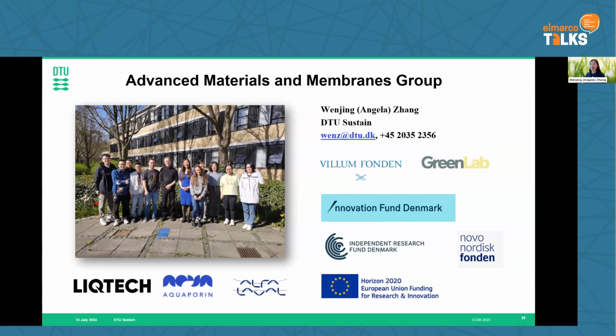Another from the audience. What do you think about core-shell nanofibers? Have you tried to use them in membrane technology, the core-shells? Yes, actually we did core-shell electrospinning, and then we did the carbonization to make a binary catalyst for zinc-air batteries. We have the paper published in Small, and we really see very unique structures. If the core is one catalyst and the shell is another catalyst, you can combine two reactions in one fiber. It's really fascinating to see what we can do with electrospinning.